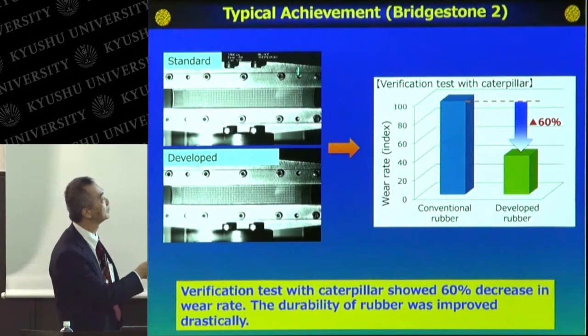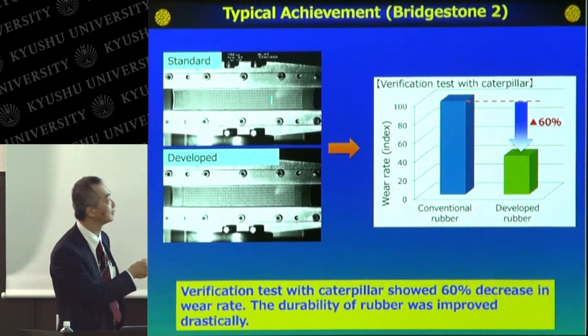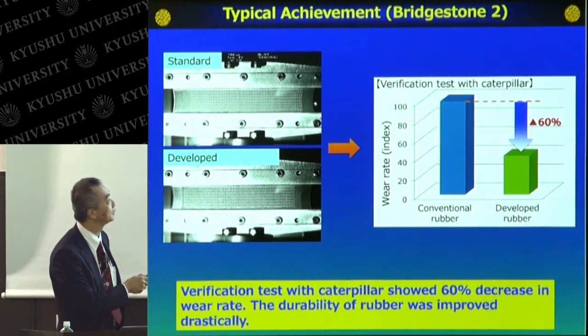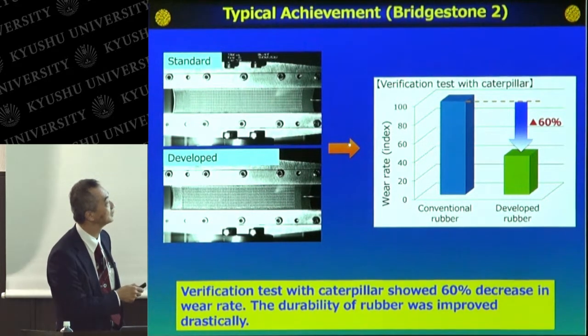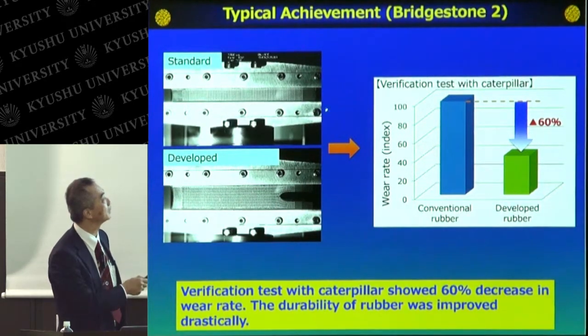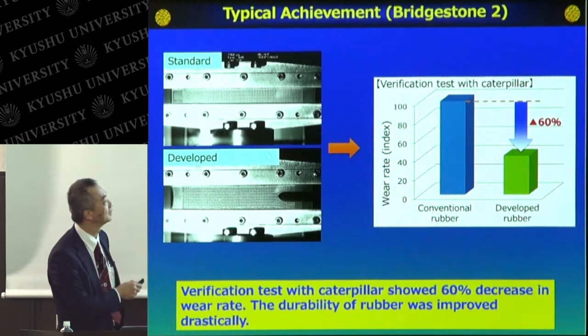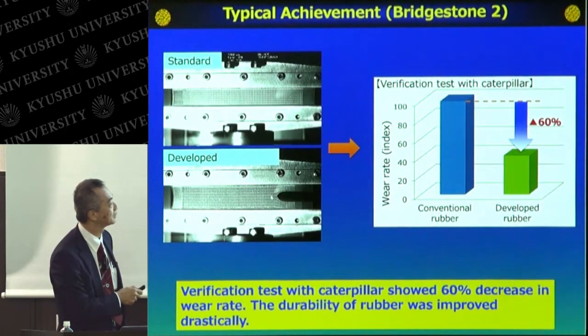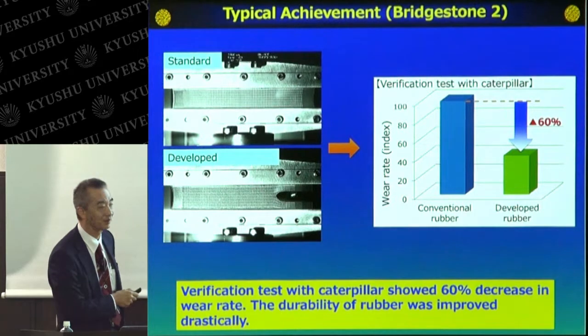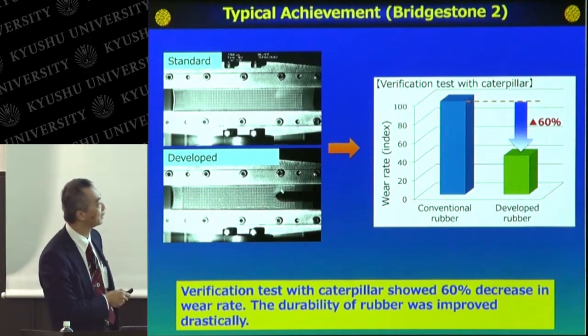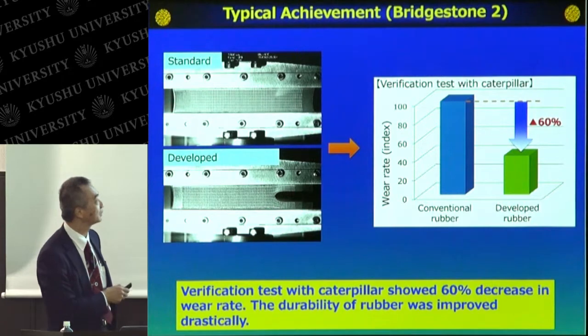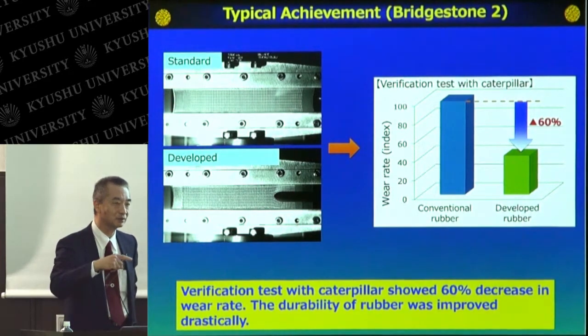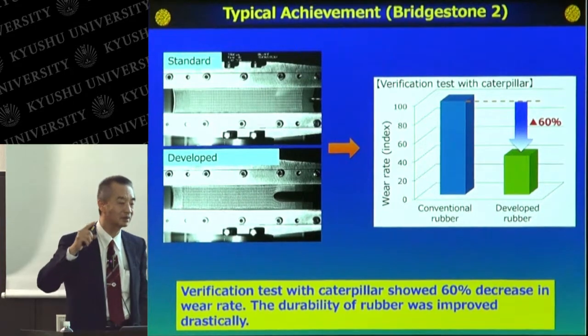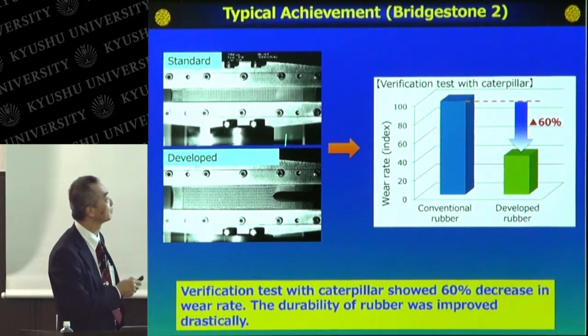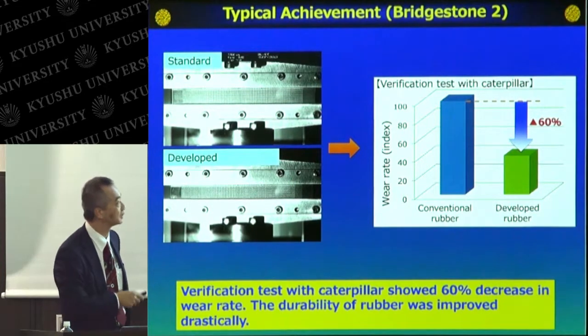So you can see that this rubber is stretched in the same way like this, and the end of the rubber is cut with a scissor. In this rubber, you can see the crack propagates very, very fast. But in this one, the crack is not propagated faster. It propagates very, very slowly. But these two rubbers show almost the same stress strain curve, but the crack propagation is quite different from each other.